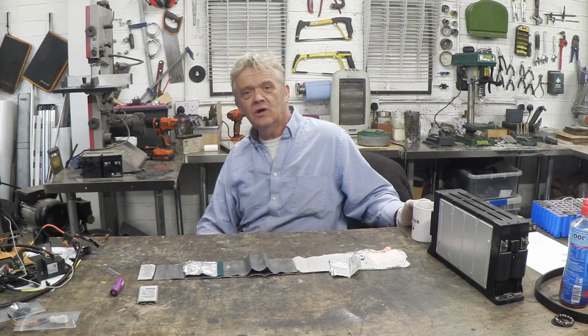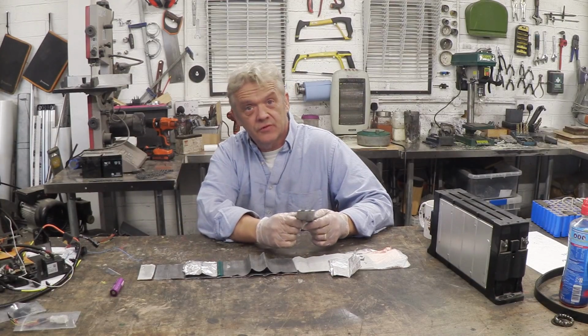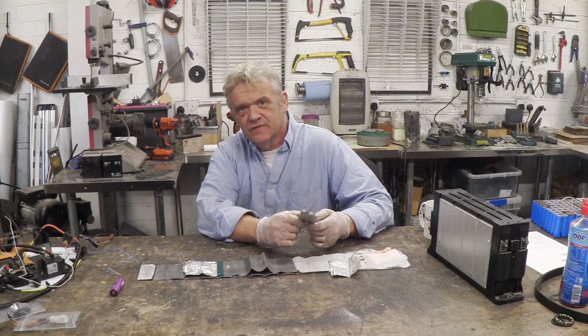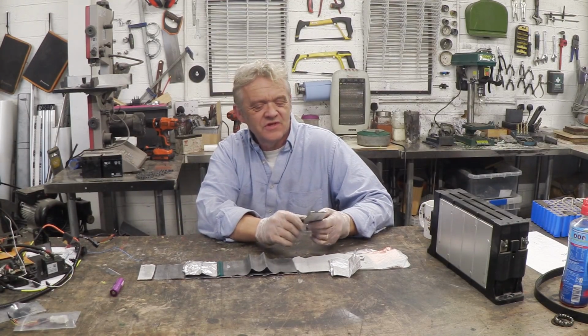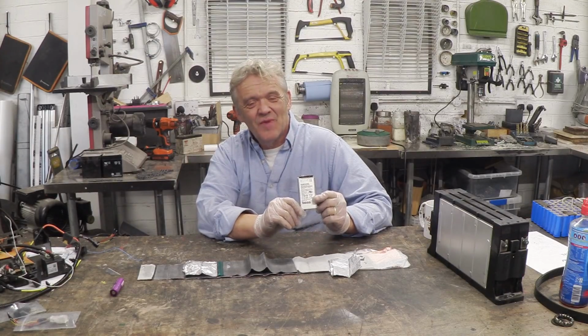If you want to know what load that's been tested on, well, you have to look at the specifications, but you can do that by going on the net. Now, the bulk of lithium-ion flavours actually have a nominal voltage of 3.7 volts and a charge voltage of 4.2 volts. However, these Samsungs have a nominal voltage of 3.85 volts and a charge voltage of 4.4 volts. And the reason I know this, it's written on the battery.